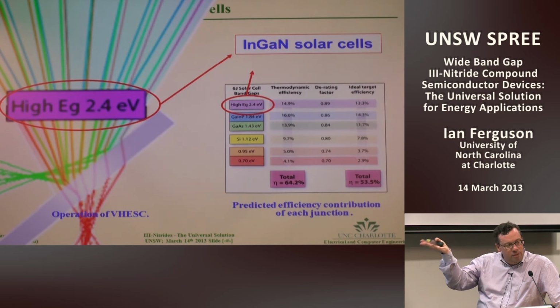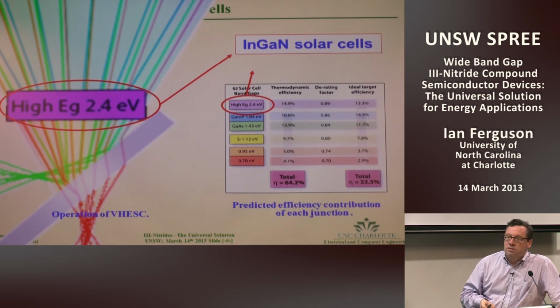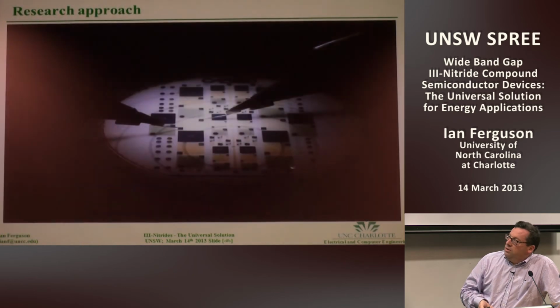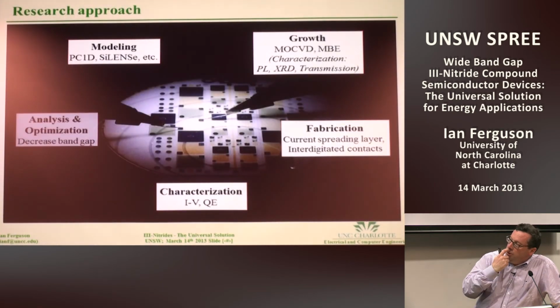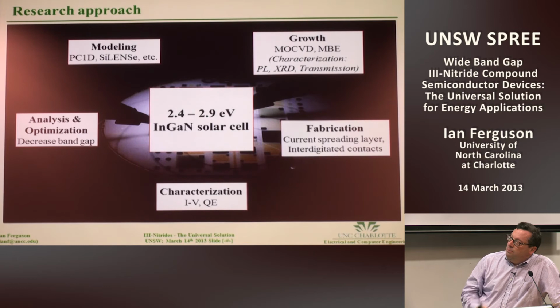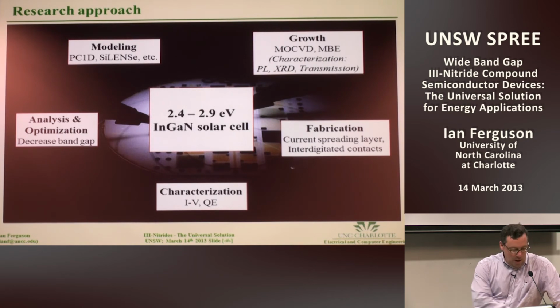At this time, people hadn't actually produced gallium indium nitride solar cells, so a lot of it was new. So the issue was primarily you had no sense of modeling and how to design for these devices. Secondly, things like the gallium indium nitride absorption coefficients weren't that well known. So you have to go in and design devices where you're trying to work out the size of depletion regions, how much indium you can get in there, and can you actually get all the absorption you want within that region.